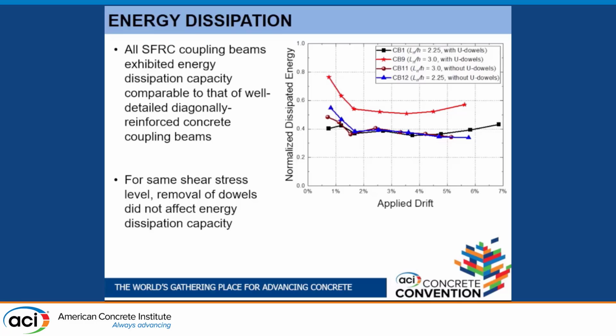So you get values roughly about 40%, except for this red specimen. This one had the lower shear stresses out of the four I mentioned, so you get quite a bit of energy dissipation capacity, over 20% higher than for the other three.